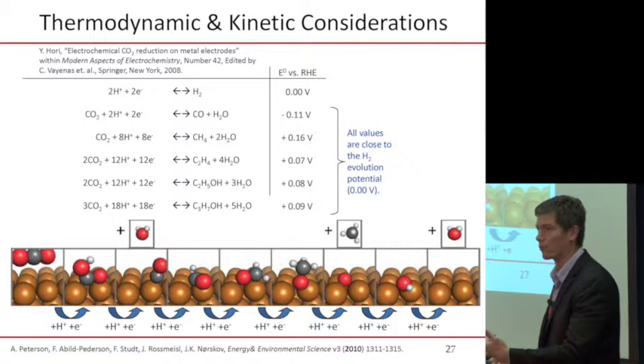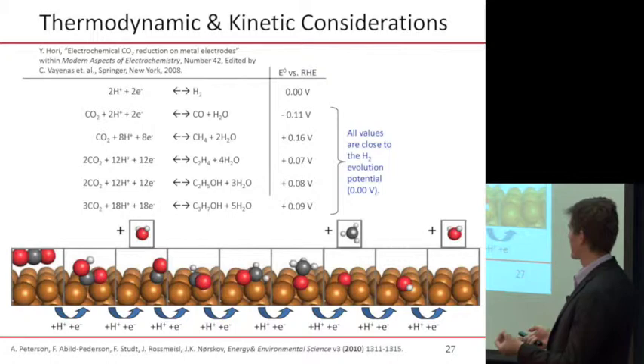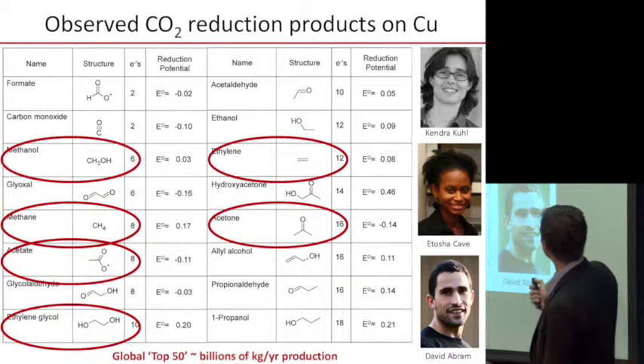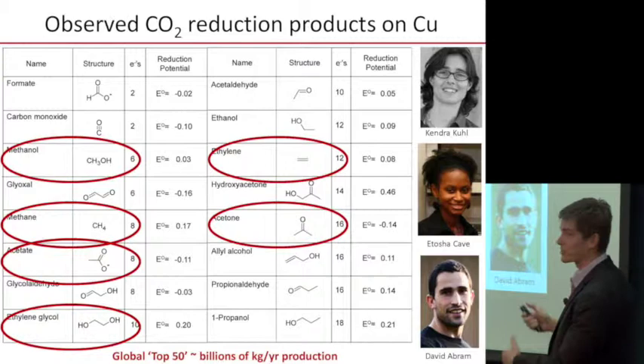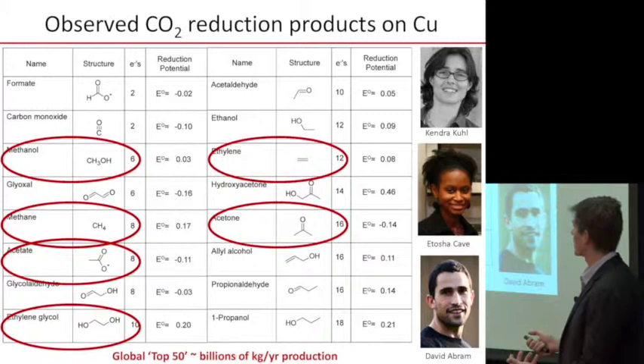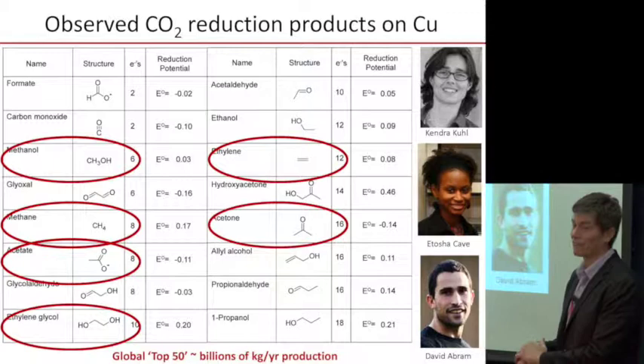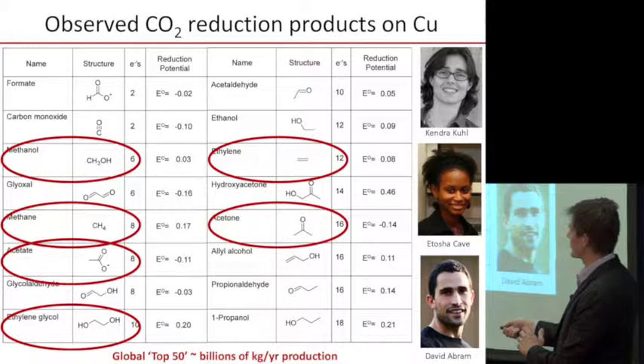We're trying to make catalysts that are just as good as the ones we made for hydrogen, but that can attack CO2. The last thing I'll say on it is, and I'll thank my three students here, Kendra, Etosha, and David. You probably heard from Etosha earlier this morning. These are my first three students to work on this project. One of the first things that they found when they were looking at copper electrodes for this process, they were able to make these 16 different compounds out of CO2, all very valuable in the chemical industry. And the ones I've circled are amongst the top 50, which means that they're getting produced on the order of billions of kilograms per year.